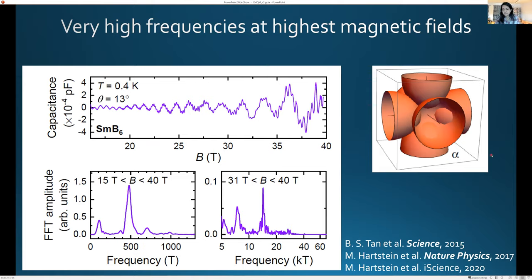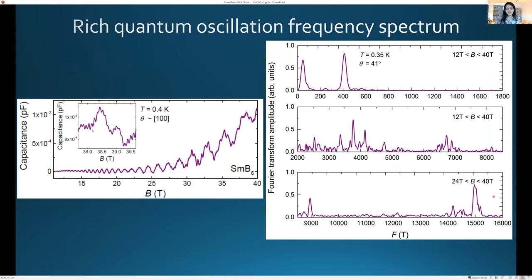15,000 Tesla. So the highest frequency implies a Fermi surface occupying almost half the Brillouin zone, which is sizable, which is why it seems like the electrons are executing large cyclotron orbits, which leaves something to be explained clearly. And this is some more data taken at a different angle, and this is just blown up so you can see the very highest frequencies.